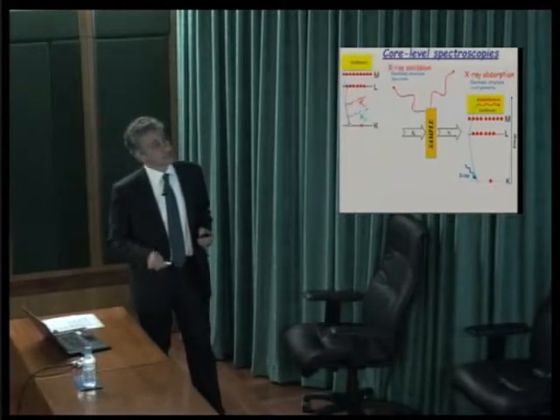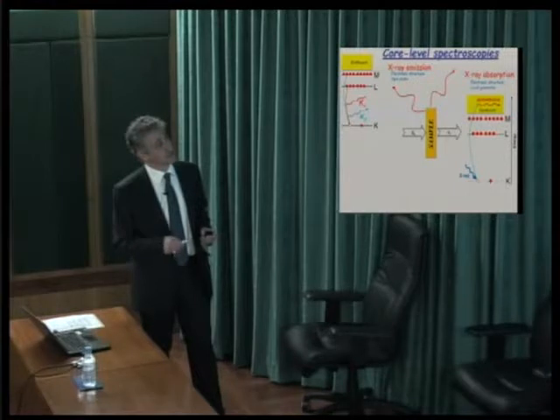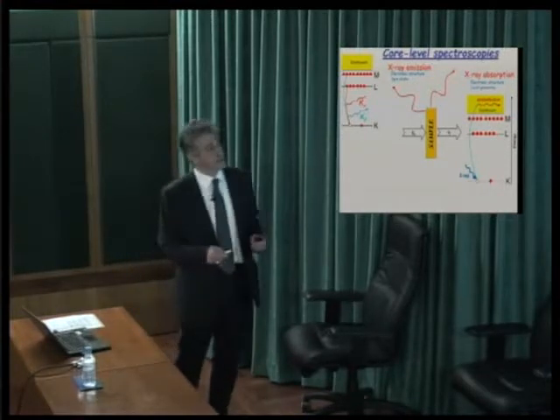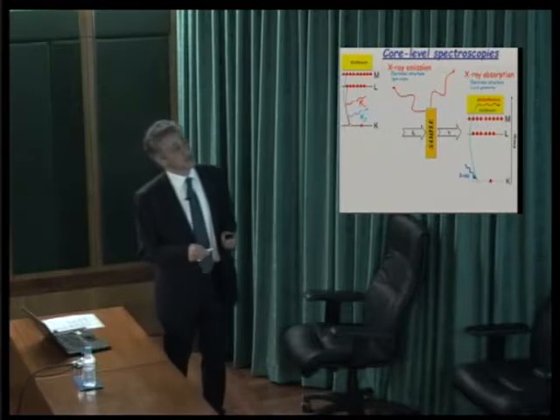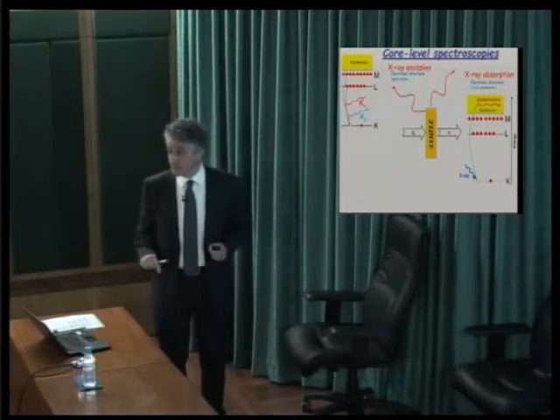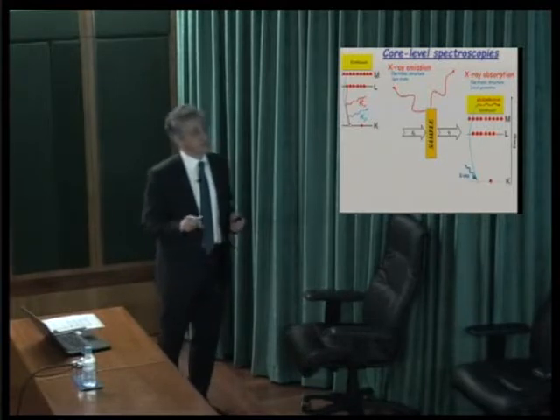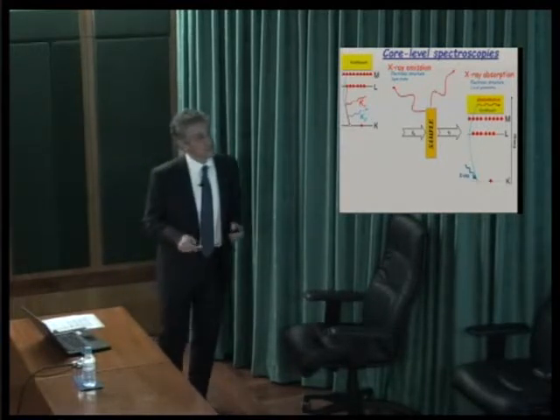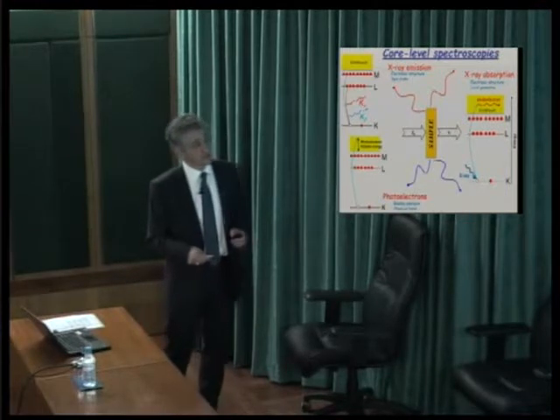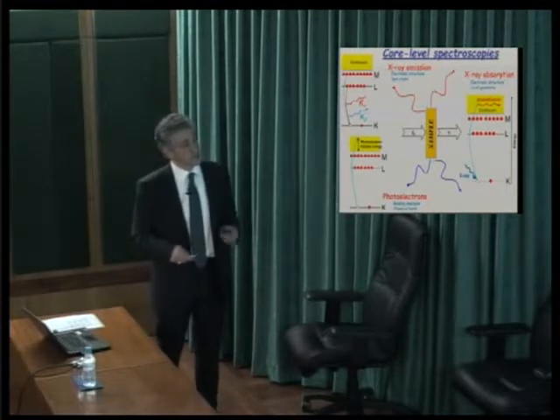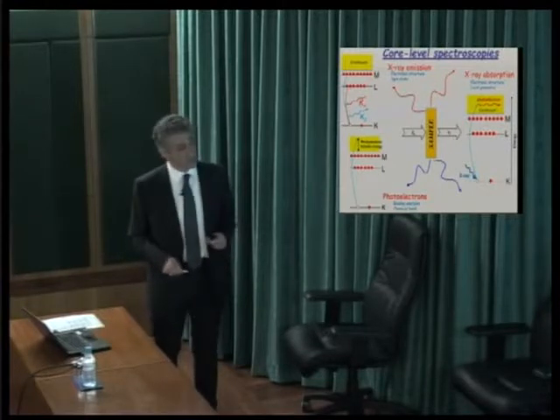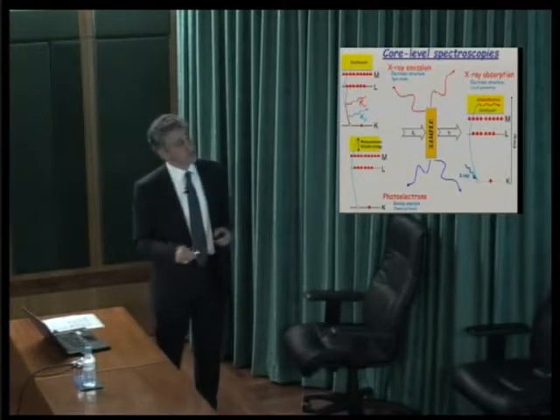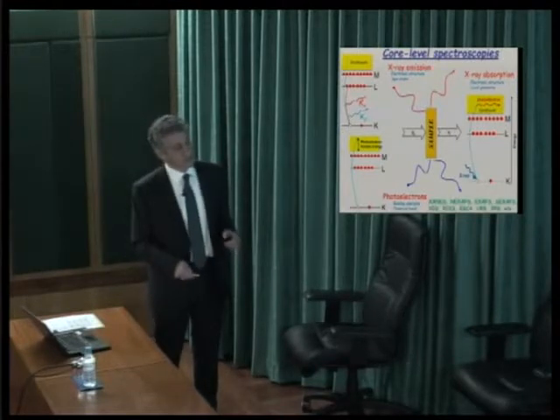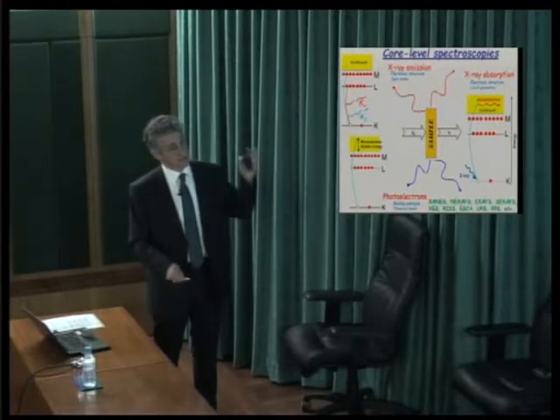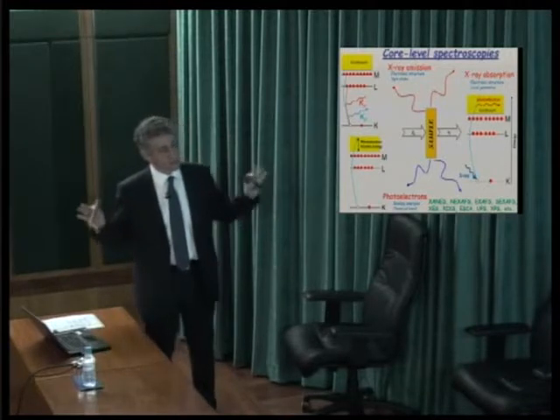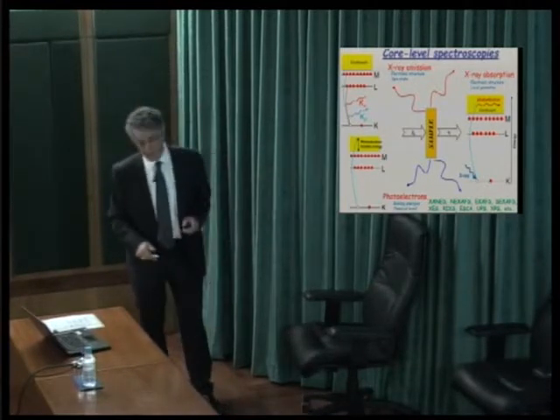Once you have created a hole in the K-shell, you can have refilling of this hole, and you get X-ray emission, K-alpha, K-beta. This gives you, again, electronic structure information, but it's also very sensitive to the spin state. It's one of the best markers of the spin state of a system. And the third thing is to exploit the kinetic energy of the photoelectron you've produced and measure it, and that gives you the absolute binding energies and also the chemical bond. So these techniques have given birth to lots of acronyms. You know, XANES, EXAFS, whatever. You know, you don't want to tell this in presence of children. It's a very, very swear, rude words.